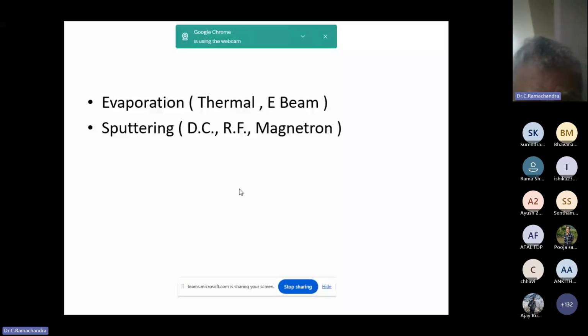For example, if I am using aluminum to deposit, the melting point of aluminum is around 660 degrees. For any temperature less than 300 or 250, the vapor pressure will be very low, so I will not have enough deposition. So I need to look for a temperature around 300 degrees approximately, so that I will have enough vapor pressure. And for aluminum, it is okay.